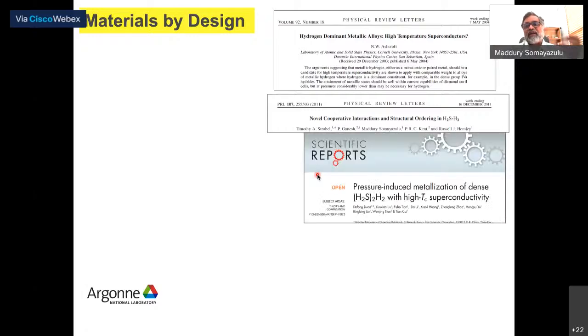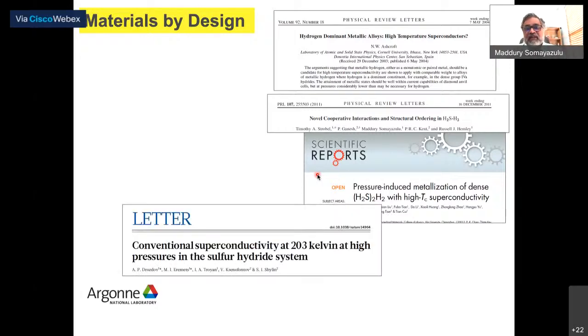That was the driving key, that the new kind of interactions which you could get under pressure gave rise to new structural ordering. What it did was that it generated this theory group to start looking at pressure-induced metallization of dense hydrogen sulfide hydride. And they predicted that actually it would be a high-temperature superconductor. So the next in the series of things was a paper which came out immediately when looking at hydrogen sulfide, which showed that at high pressures, you could get a transition temperature of the order of 203 Kelvin in hydrogen sulfide itself.